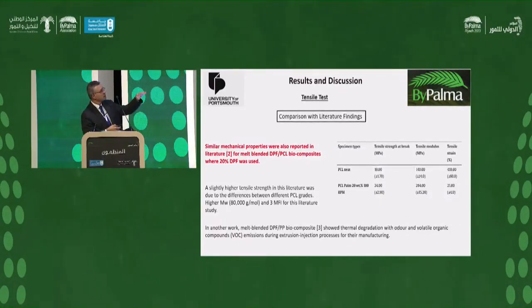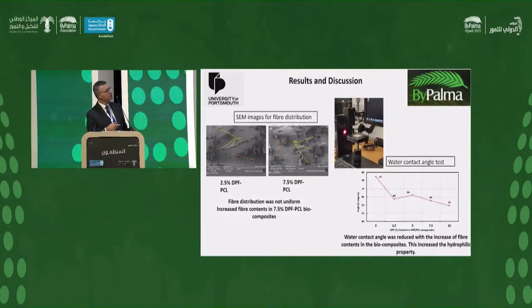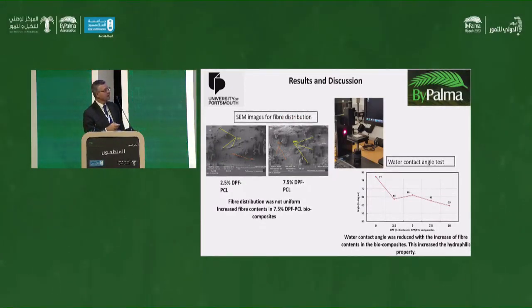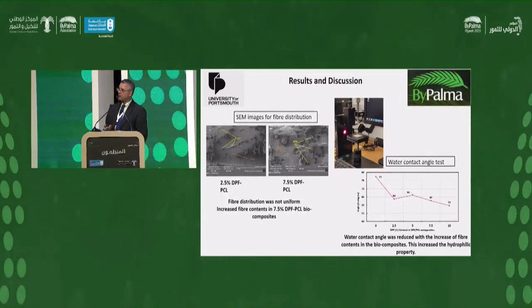So this is just a quick comparison of literature, and here we use contact angle measurement to see the wettability. As you can see, an increase in date palm fiber has increased the wettability or decreased the contact angle. So obviously the hydrophilicity of date palm fiber would increase the wettability, which is good.